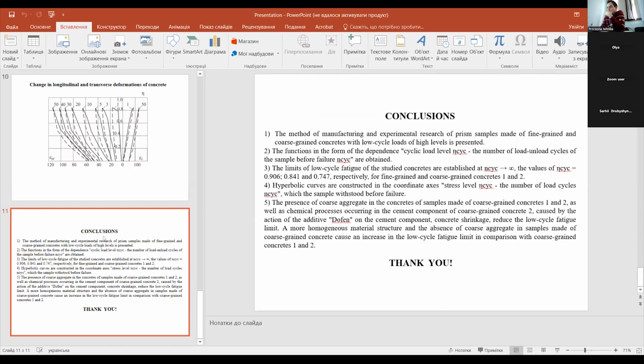Conclusions. The first: the methodology for experimental studies of prism samples made of fine-grained and coarse-grained concrete under low-cycle loading has been presented. The second: the function in the form of the dependency between cycling load level and number of loading-unloading cycles until failure was obtained. The third: the low cycle fatigue limits of the tested concretes were established as eta cycle equal to 0.906, 0.841, and 0.747 for fine-grained concrete, coarse-grained concrete of the first type, and coarse-grained concrete of the second type, respectively.